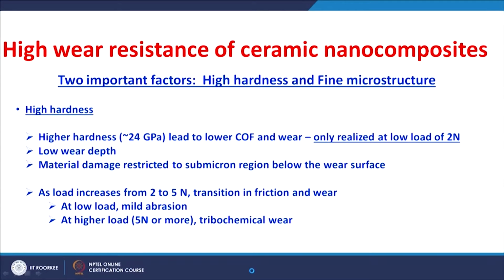So, let us understand the wear resistance of the ceramic nanocomposites. Two important factors have to be considered. Number 1, the high hardness, and number 2, fine microstructure. The extremely high hardness obtained for this nano ceramic composite, around 24 gigapascal, leads to lower friction and wear, but this is observed only at a lower load of 2 Newton. At lower load there is very little wear, characterized by a low wear depth, less than 1 micrometer. The material damage is restricted to a submicron region below the surface,